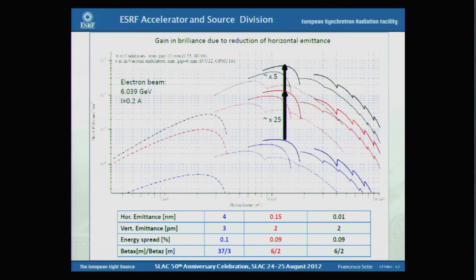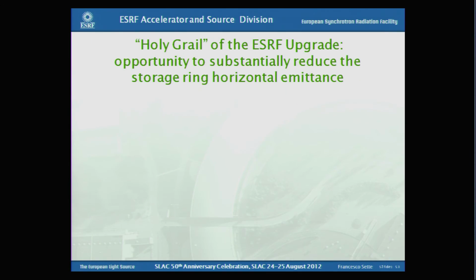I also want to mention that out of these studies, aimed to see whether one can have a fully diffraction limited source, studies have been also carried out not only for a 150 picometer horizontal emittance lattice, but also for 10 picometers. And as you can see here, the brightness down to something like 100 picometers scales more or less proportionally to the horizontal emittance. But when you go below 100 picometers, the gain goes more or less as the square root of the emittance reduction because of the effect of diffraction limits in the source that starts to be observable. So this is somehow the holy grail on which the ESRF is working today, and the opportunity to substantially reduce the storage ring horizontal emittance.